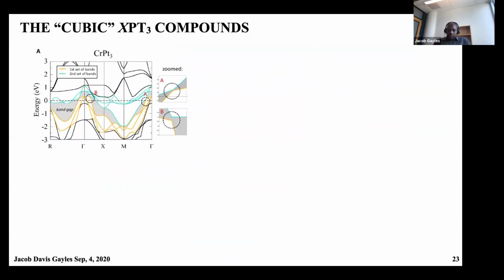So now let's get back to the theory, specifically these X platinum compounds, and we focus here mostly on the chromium platinum 3 because it shows the most interesting effects of the 3 compounds listed above. And what we find is that we actually have 2 sets of bands that contribute to this anomalous Hall effect. The first set is shown here in orange, and the second set in blue. And these are actually topologically disconnected.